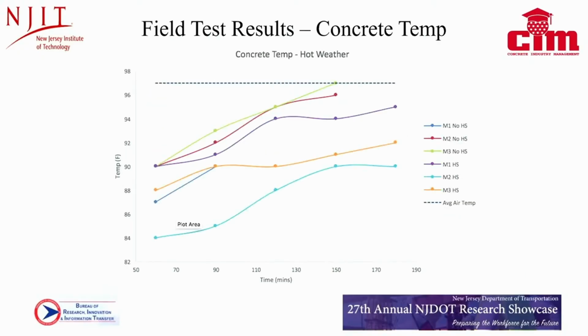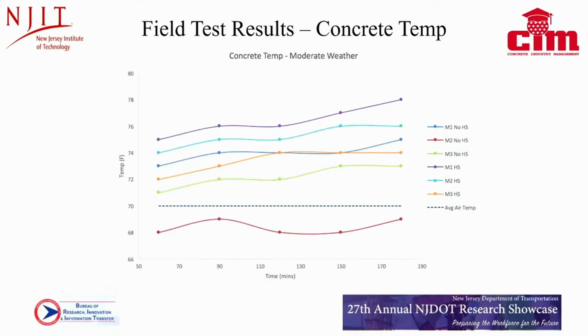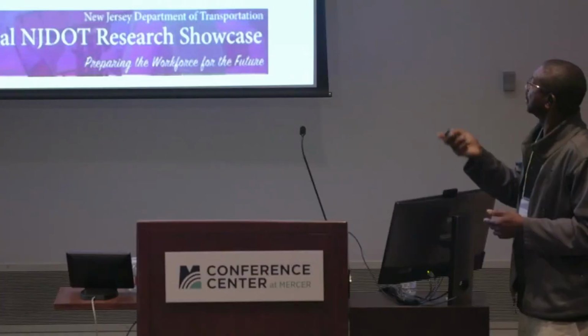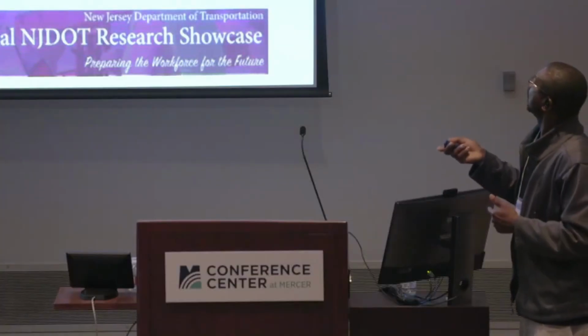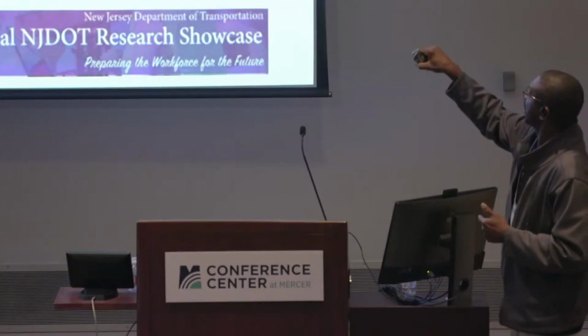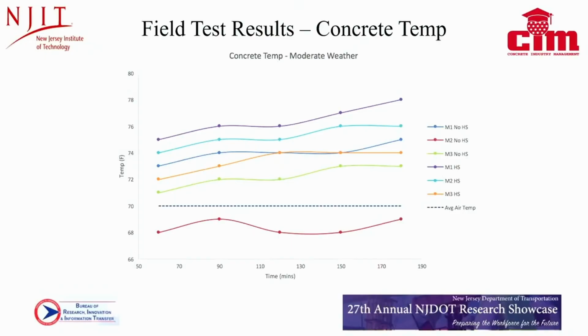The temperature, if I recall correctly, we started out, freshly mixed concrete started out at about 85 degrees. And of course, as hydration kicked in, it increased by about 10 degrees over the span of those 2 hours, which is not bad considering. Okay, temperature here again. This one is no hydration stabilizer, and as you can see, with the hydration stabilizer, I was able to maintain it fairly constant.